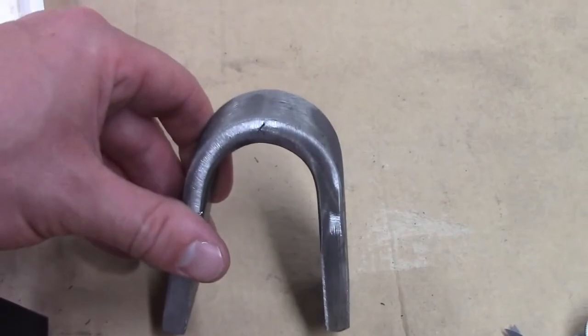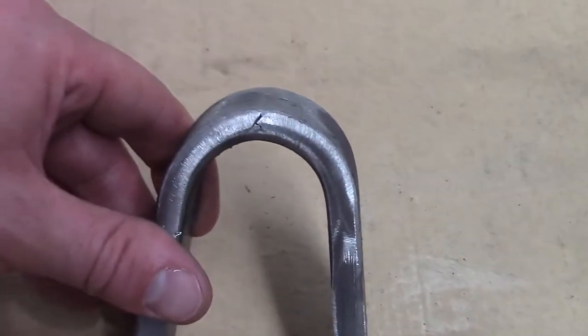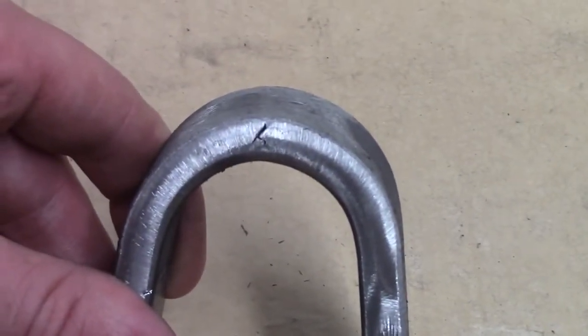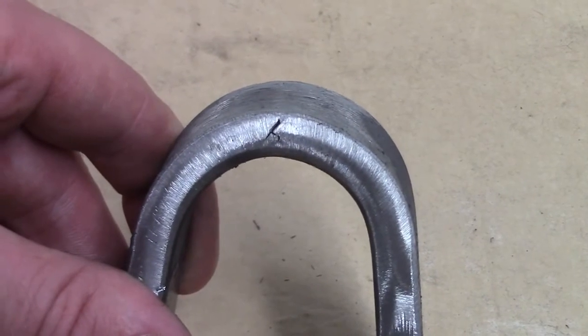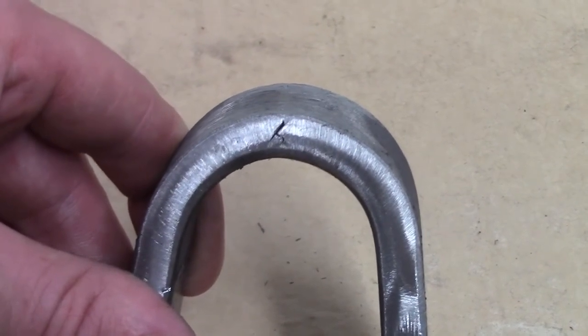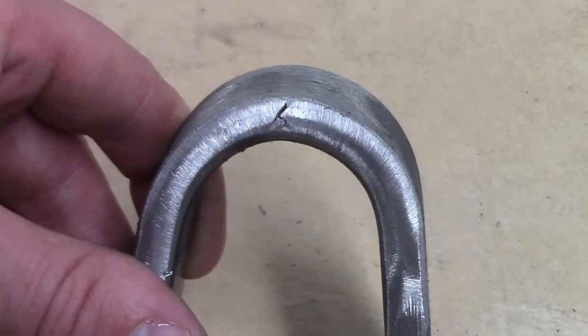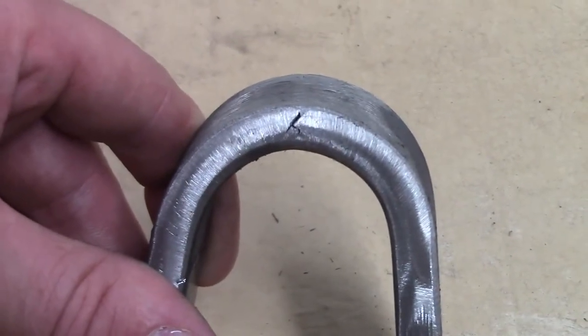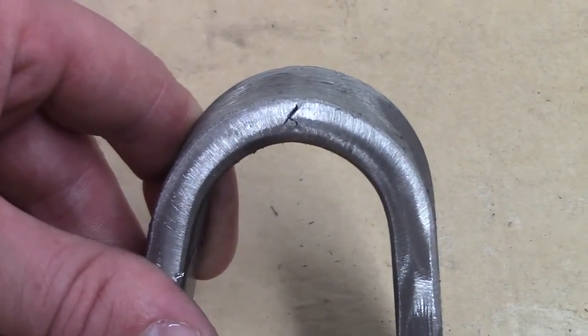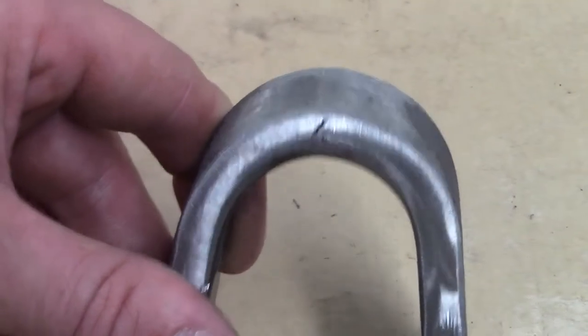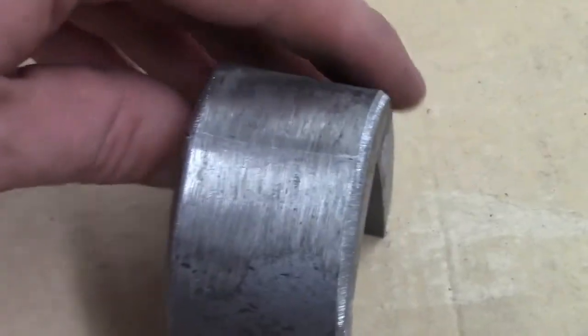The other crack we have is there's a corner crack that measures out to 0.2. And we know, according to our code, that you're allowed to have up to 0.25, quarter of an inch on the corner, unless it's from visible slag, which we're using MIG, so there is none. So this bend is acceptable.